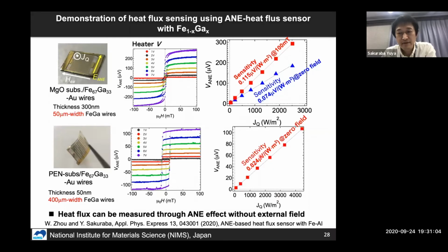Although the observed sensitivity is still not so large because the width of the iron gallium wire is very large in this prototype of the device, there is still large room to improve the sensitivity of this heat flux sensor by reducing the width of the ferromagnetic wire. And of course, if we can find a new material showing a higher anomalous Nernst effect, we can realize much higher sensitivity in this heat flux sensor.